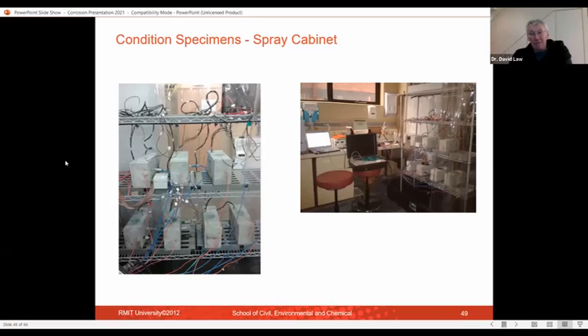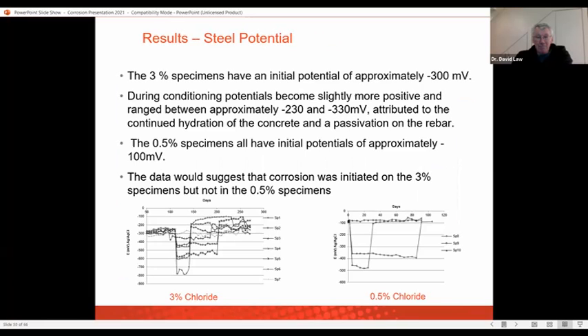Here again, these specimens were conditioned in a spray cabinet over that period of time. What we saw with these by plotting are steel potentials. This area at the beginning is what is happening with those potentials before we apply the cathodic protection. You can see that generally they're drifting a little more positive as they passivate after we've cast them, but a few of them we start to see dropping. Some of them were starting to corrode, and most of our 3% specimens we felt were corroding, but most of our 0.5% specimens in these short-term trials had not been able to establish corrosion sufficiently at the time we applied the CP for the student who was doing this work.